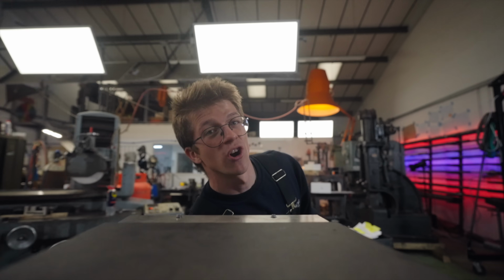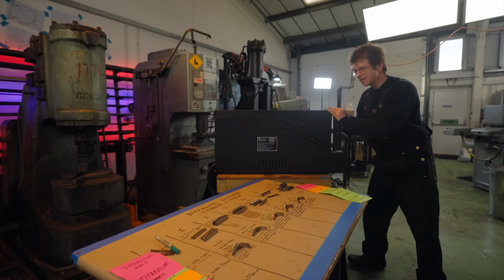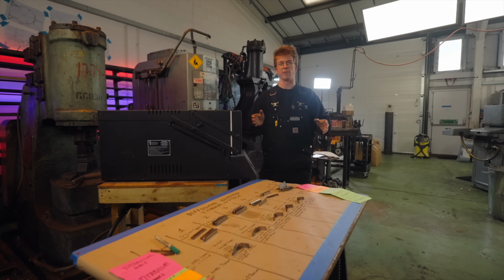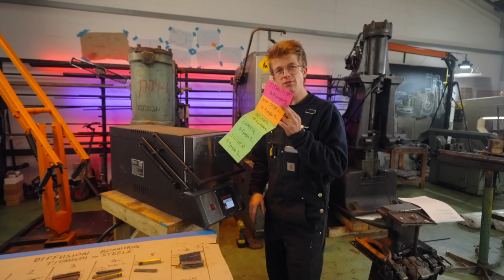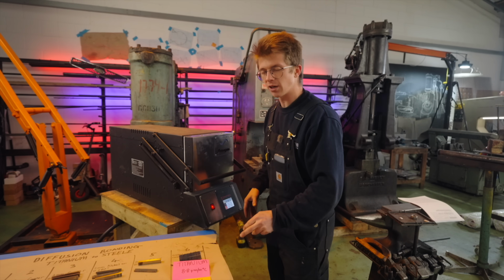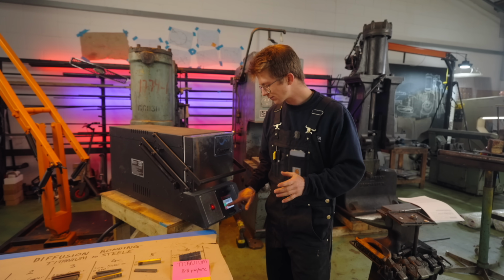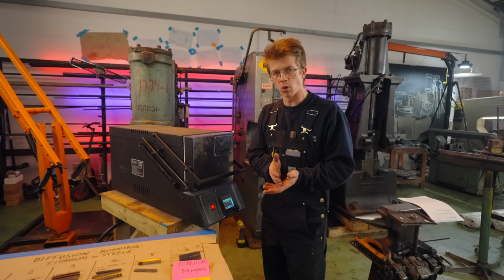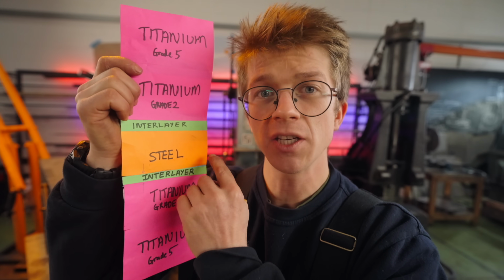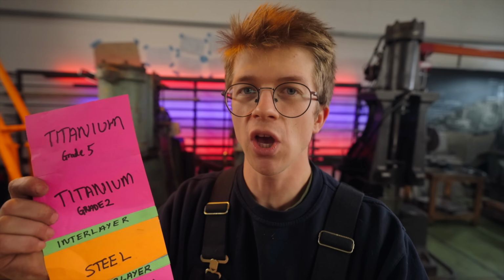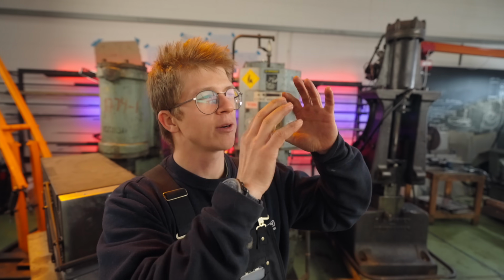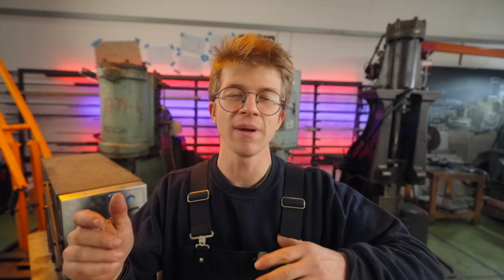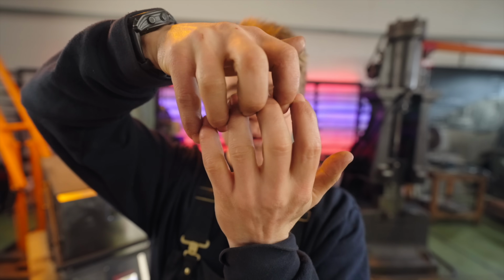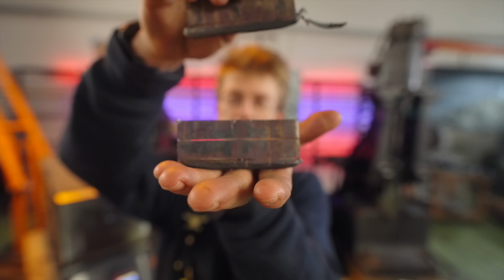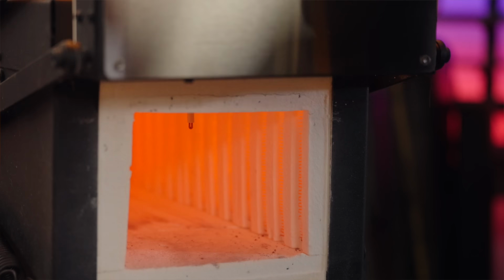The next thing that I want to try is hardening them. And the reason kind of goes back to the earlier topic of the coefficient of thermal expansion. Given that all these materials respond to heat differently, what happens when we have to quench it in order to harden the steel core? How is the joint interface going to react to an extreme thermal shock, where the titanium, the interlayer, and the steel are all trying to contract in different ways? The steel more than the titanium, the interlayers more than either of them. Are we just going to shear those bonds apart and add to our growing pile of scrap?